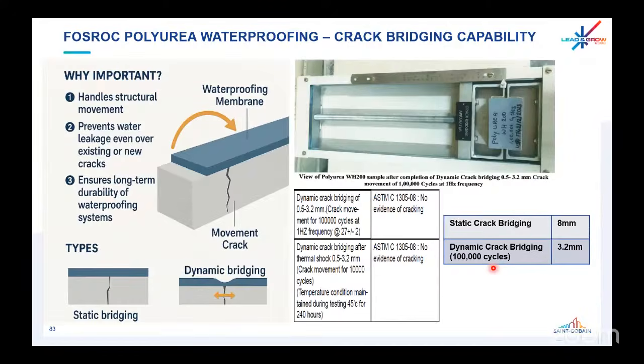And this product is highly elastomeric in nature. It has got a good crack bridging property also. It has been tested for static crack bridging of 8 millimeters and dynamic crack bridging of 3.2 millimeters. It means that when a waterproofing treatment is applied on this concrete substrate, in the event of any kind of cracking in the substrate, these products are able to withstand the crack movement without compromising on the waterproofing integrity of the structure.